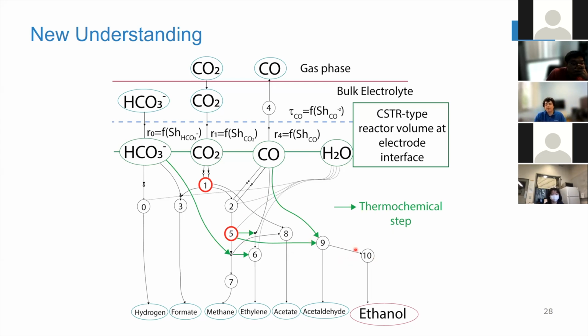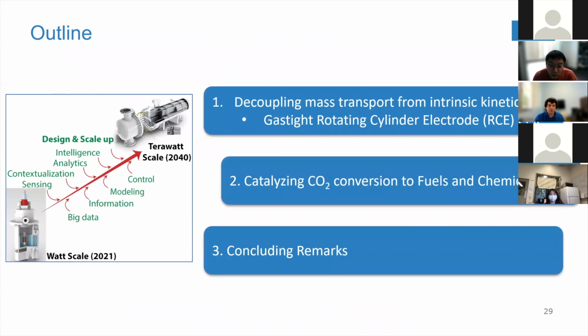So far, we believe that the CC coupling is just 2 CO sitting on the surface. But this is just an explanation, although there is some spectroscopy evidence. Most of the DFT tools that we have right now cannot account for that sort of dynamics of adsorption and reabsorption of reaction intermediates. And so I think we're challenging what is believed on the CO2 reduction mechanism for this process.